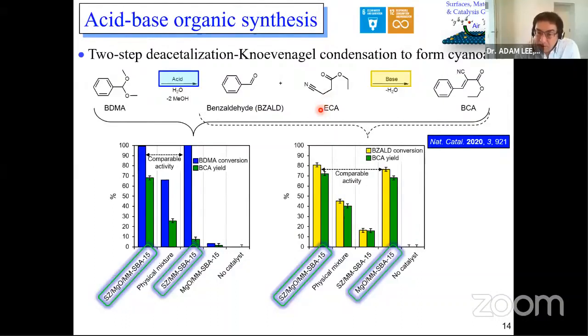If you take a solid base catalyst, so pure MgO, just to say this part here is just a silica framework. So here it's magnesium oxide on silica. Here it was sulfated zirconia on silica. So the framework itself is inert. What you find is that the MgO catalyst is very active for this step here. And so is our spatially orthogonal catalyst. It's also very active for that step here as well. So our spatially orthogonal catalyst can do both steps, the acid step and the base step.